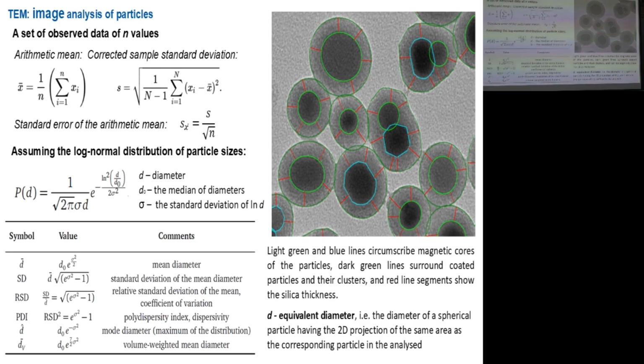If you formulate your log normal distribution like this with this type of sigma, then this sigma parameter is the standard deviation of the natural logarithm of the size. It is not the standard deviation of the size. Alternatively, if you introduce logarithm into this formula of some sigma, it won't be again standard deviation of the size, but it will be so-called geometric standard deviation, and it is not trivially related to the standard deviation of the size. So do not use units for such sigmas, and you have to understand that this sigma is really the deviation of logarithm.